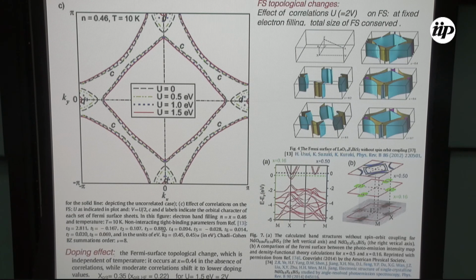Here on the right side, you see some calculations done by Usui with the bare bands. And actually, the Fermi surface they obtain describes quite well what is known from the materials. And these are as a function of increasing doping. So this is 0.2 doping in this lanthanum oxygen fluor bismuth S2. And here you notice that you're having a change of the topology of the Fermi surface. In this case, it is doping 30% and 40%. So with these bare bands, they get a critical doping where you get this Lifshitz transition. And then when you have more electrons, the Fermi surface doesn't change much more. So, I mean, it conserves.